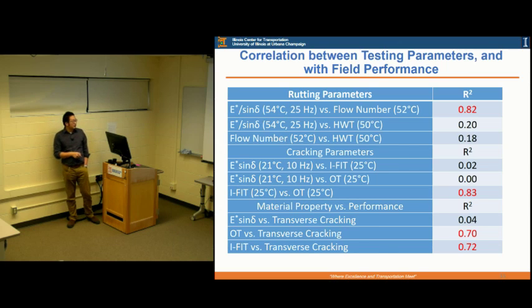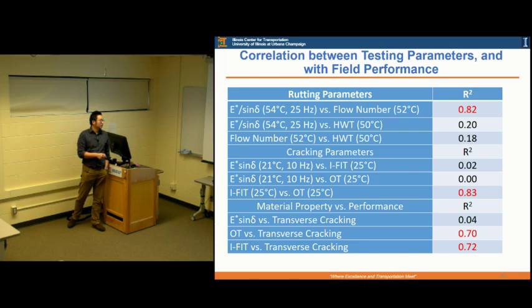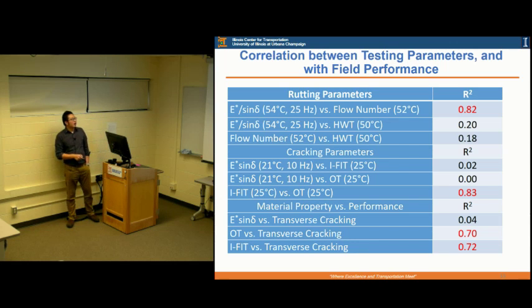Good correlation with the overlay tester. But this E star is not correlated with the iFit or the overlay test. As I said, the E star is again in the non-destructive range, while the cracking test is just beyond that point.